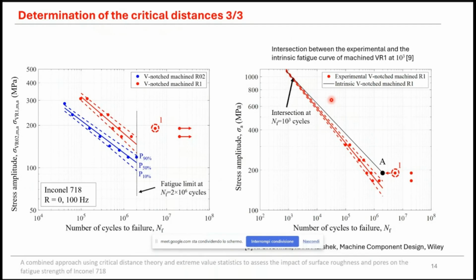This assumption could be motivated considering that at a low number of cycles, plasticity plays a key role in redistributing the stresses, so the effects of defects can be considered negligible. So once the intrinsic fatigue curve of the machined blunt V-notch specimen was obtained, it was combined with the experimental curve of the severe V-notch machined specimen, and the critical distances were identified.